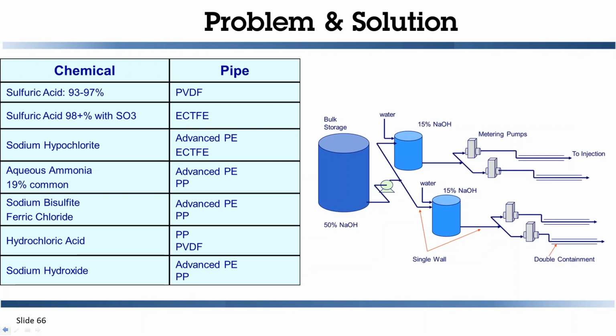Here's a few common chemical applications. So we have sulfuric acid at 93 to 97%. We would recommend PVDF for that. Anything up to 85%, we can actually use polyethylene. And at low concentrations, you can use pretty much any plastic. Sulfuric acid, 98%, as we discussed, it's going to be ECTFE. For sodium hypochlorite, advanced PE or ECTFE. Aqueous ammonia, 19% is the most common. We have advanced PE or PP. And then we have sodium bisulfite, ferric chloride, hydrochloric, sodium hydroxide, all with different options based on the customer's acceptance for price, size considerations, and total available pipeline they're installing.